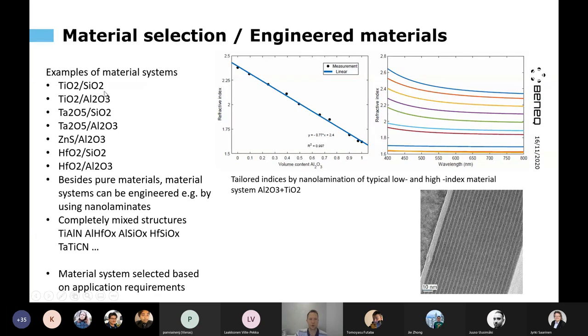In addition to just these pure materials, we can also make engineered materials by making nanolaminate structures, as shown here on the right hand side. Using in this example aluminum oxide and titanium oxide, and making these types of nanolaminate structures, we can generate artificial materials that have index something between that of titanium oxide and aluminum oxide. And we can see that we can quite linearly scale whatever we like between these two materials. And really it looks like this under the electron microscope, that in this case there is about 3 nanometers of titanium oxide, which is the dark material, and then about 7 angstroms of aluminum oxide, the light white lines between.